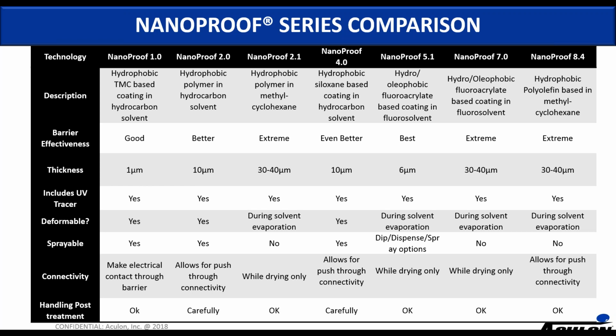Here we have a chart that breaks down some of the basics of the different NanoProof series products. I'm not going to get into every detail, but a PDF of this presentation is going to be emailed out so you can have a look at it later. We have a wide range of options from NanoProof 1, which goes down fairly thin, around 500 nanometers to a micron in thickness, and offers basic levels of protection, IPX2 to 3, and is extremely easy to apply. We have some mid-level protection options, NanoProof 4 and 5, which are more in the 5 to 10 micron thick range, offer IPX3 to 5 levels of protection, and are great options, very easy to apply. Again, great options for those of you looking for splash and sprayed water protection and some humidity robustness.